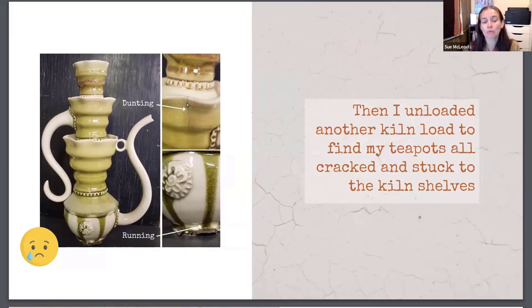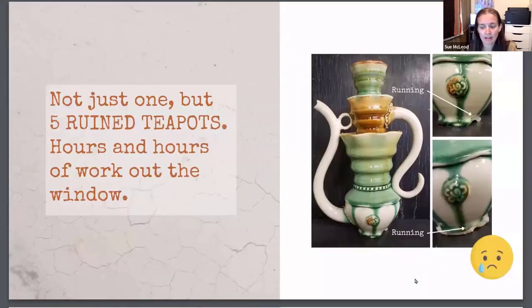There was dunting. So dunting is when your clay cracks because the thermal expansion relationship between your glazes, they're kind of pulling against each other and creating a lot of tension. And sometimes it's enough tension that it can actually crack your pots. So they were all stuck to the kiln shelf. Some of them, even if I could grind the drips off, which I couldn't, the tops were cracked as well. So another sad face. Here's another one of those teapots. So 5 ruined teapots, hours and hours of work out the window.